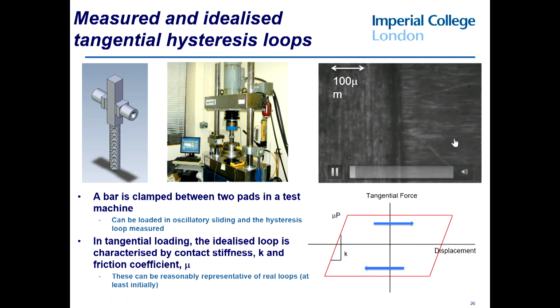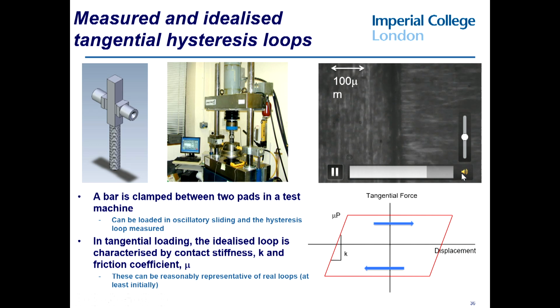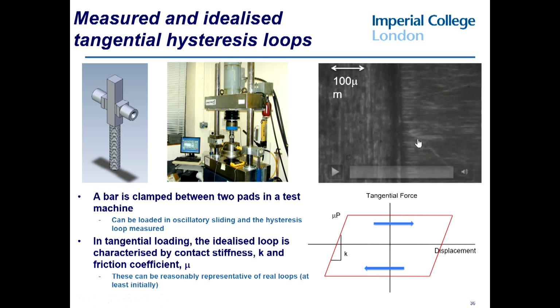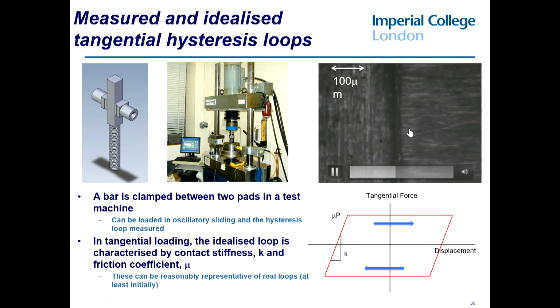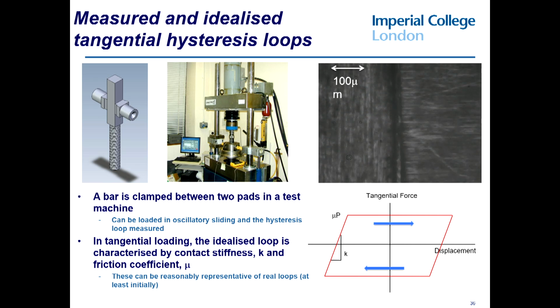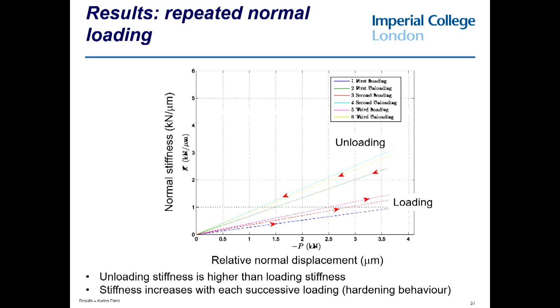And here's an example of, again, zooming in very much on a contact. You can see a little bit of slop in the system, but we can extract from that the kind of displacement data that we need to plot stiffness. And what we find is that contacts change. Again, so not only does the friction coefficient change, but also the stiffness of the contact changes.